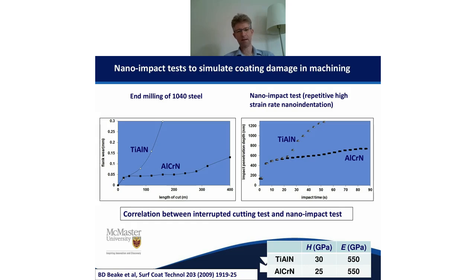So another example here, again comparing two different cutting tools. You can see on the left is the cutting tool test, and on the right is the impact test. And what we can see here is that this coating, this titanium aluminium nitride, starts off about the same as the other coating, but rapidly starts to fail more quickly. This one, this aluminium chromium nitride, shows a much longer sort of fatigue period.